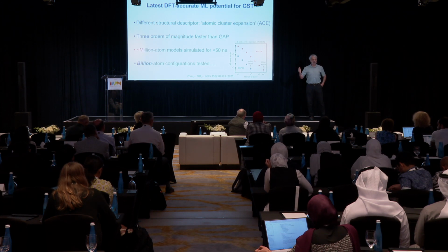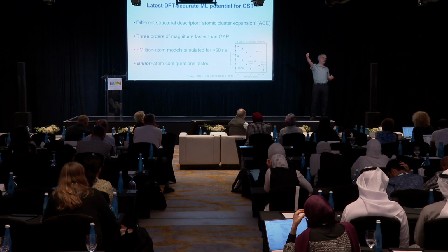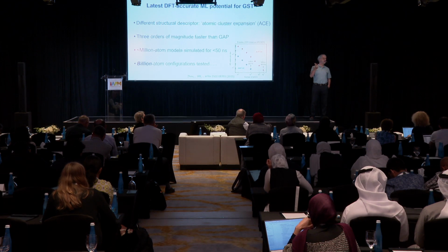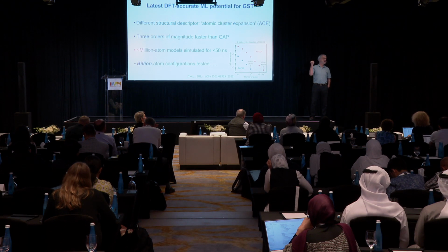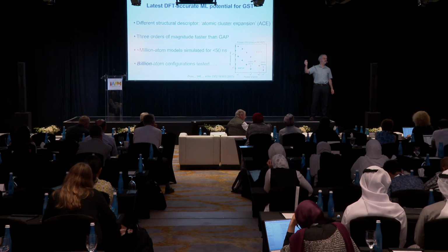Well, neuromorphic is just like the other thing, except you have this continuous range of glass to crystal. It's not 100%, 100%, it's a continuous range. So you're still worrying about how long it takes to switch between a crystal and a glass. That's the limiting stage. And it's material limited, as I've shown you here, like 10 nanoseconds, 5 nanoseconds. Doesn't matter if it's neuromorphic or flash type memory.